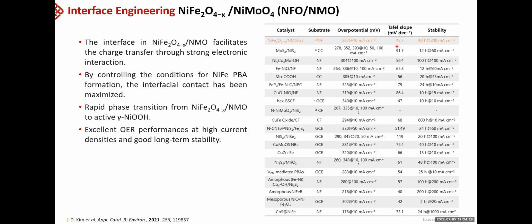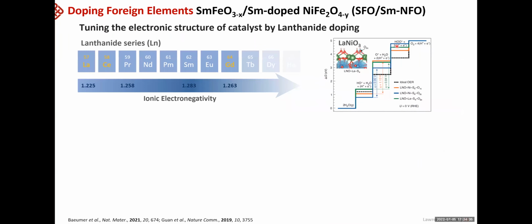The next question we had was whether we can combine these two effects together. So we were interested to have both effects, interface and the doping. And as a doping element, we chose a lanthanide species because the lanthanide is an electron-rich species because of the empty 5d or 4f orbitals, and they show very rapid electron transfer. There are many reports making use of lanthanum or cerium or gadolinium. But actually, if you look at the ionic electronegativity, the samarium has very good electronegativity. So that's why we chose samarium as our dopant.